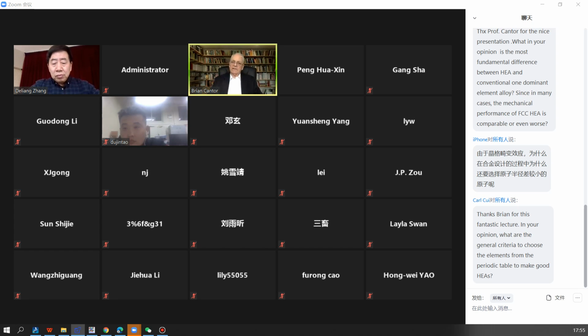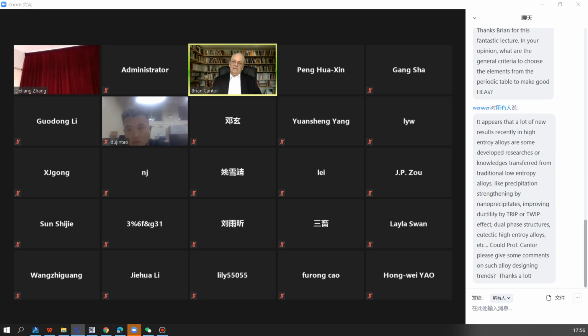So you've got local lattice strains, which give resistance to diffusion and resistance to dislocation slip, and some other properties of that sort. By the way, there are some interesting electrical and magnetic properties caused by those local variations as well. But if all the atoms are the same, as in pure copper, you don't get those effects. So you want those effects. On the other hand, if you put in atoms with bigger differences in size, those differences lead to the breakdown of the face-centered cubic crystal structure, and you start to have other phases, and the material begins to be multi-phased.